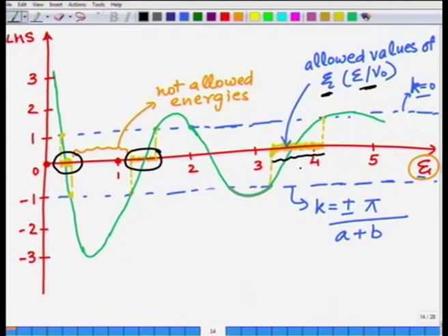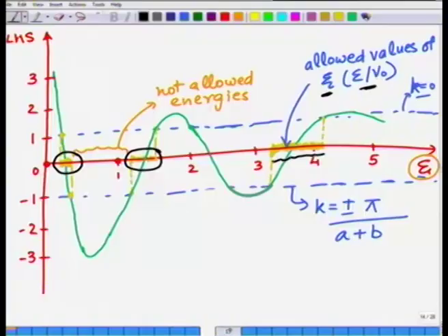And conversely, of course, as V 0 decreases, or energy increases, the bandwidth becomes larger and larger, which you can visualize: if I have a small potential, then once I cross that potential, once the total energy is much, much greater than V 0, it will be like a free electron. It will not see the potential, but when I am coming close to that potential, I will see different bandwidths, and as I am going deep into the potential well, my bandwidths will become narrower and narrower to the extent that they will become discrete. All right, which we will see.